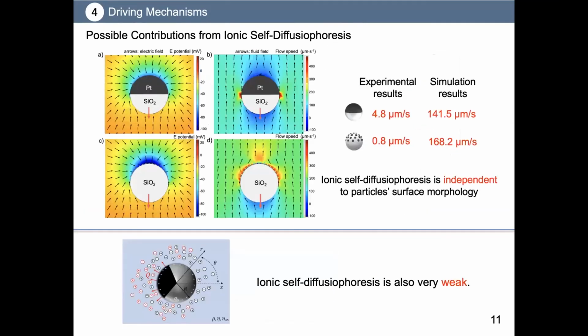As for the ionic self-diffusiophoresis, we performed simulations to showcase the effect of the surface morphology on motor speed. Theoretically, silica-platinum film and silica-platinum nanoparticles should have similar speed if the ionic self-diffusiophoresis is a dominating contributor, because after annealing, despite the continuous film being transformed into discrete platinum particles, they are still coated on the half of the microsphere and catalyze a similar amount of hydrogen peroxide, and they almost have the same zeta potential.